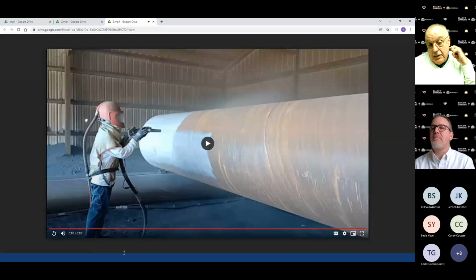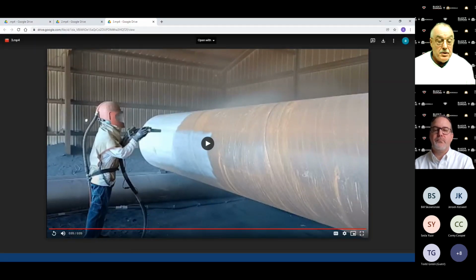Again, it does a good job, even at those fewer turns. Now, on the micro valve, when you go from 3.5 to 3 turns, your consumption rate goes down, all things being equal. So theoretically, when you have the minimum turns on the micro valve, the abrasive metering valve, the material is going to last longer. The pot is going to last longer. Instead of 40 minutes of blast time on, say, a 600-pound pot, it might go 45, it might go 50 minutes. So that's the difference.